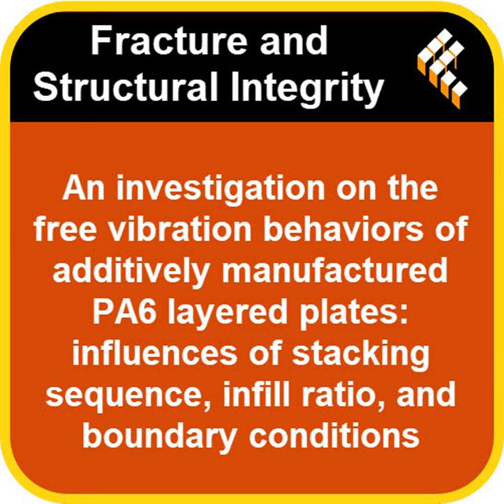Right. So if you're designing a functional PA6 part where vibration is really critical, maybe for noise reduction, avoiding that dangerous resonance, or ensuring durability, these findings give you real practical control. You can actually tune its vibration behavior, not just by printing with more or less plastic overall, but strategically by how you distribute that material in layers. The stacking sequence. And by seriously considering how the part will actually be mounted or fixed in place. Yeah, it moves beyond just printing a cool shape to actually engineering its dynamic response based on both its internal structure and its external constraints.